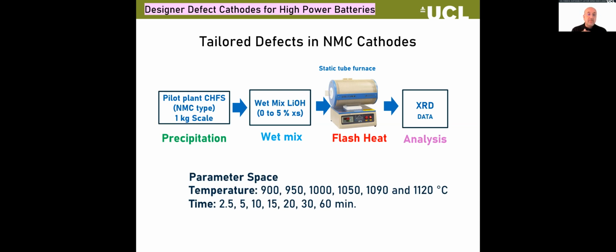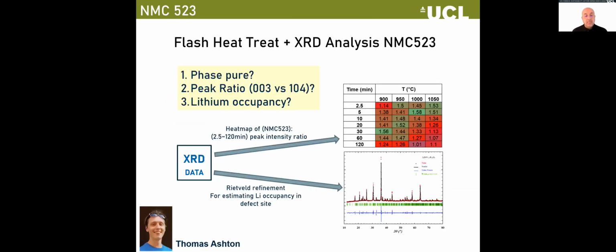And we now have a current Faraday project, which is taking this up and scaling what we've achieved. And I'll tell you about it. So what we were doing was taking these nickel manganese cobalt materials, or nickel cobalt alumina, NCA. These are high power cathodes. And essentially we were mixing them with lithium again. And then we were doing flash heat treatment, and we were doing XRD data. And what we were trying to look at was a particular thing.